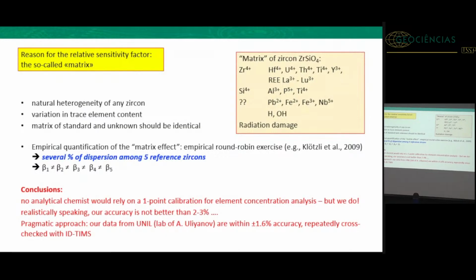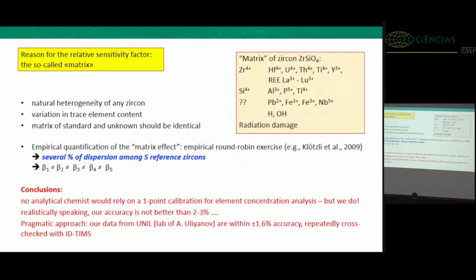It has been done a few times with a horrible outcome. So this is just one example. You take 5 reference zircons, you take 1 as primary standard and measure 4 as unknowns, then you take the 2 as primary standard and measure the others as unknowns, you do a round robin test. So Klötzli came up with a maximum of 7% variation. 7! So you see your Neoproterozoic granites plus minus 7%. This is what you can say as an accuracy, but it's mostly better than this. So it's a bit too pessimistic.